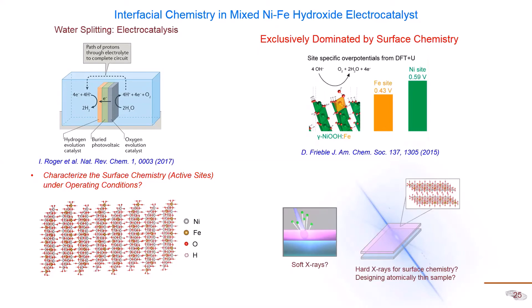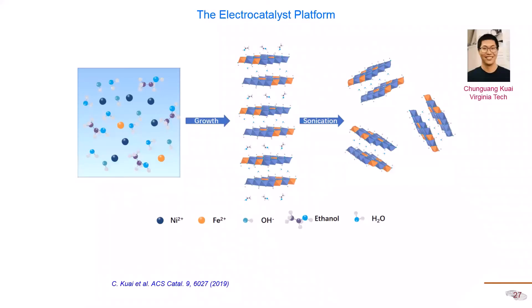Chunguang Kuai performed better visualization through wavelet transform analysis of the EXAFS to differentiate iron-iron versus iron-nickel neighboring. Upon charging to 1.6 V, the iron-nickel coordination (neighboring) disappears. Upon recovery, it shows up again. These are snapshots of experimental evidence showing reversible segregation and incorporation of iron into the lattice. We then designed a protocol leveraging this reversibility — periodically applying a short two-minute reduction step at 1.33 V during operation to incorporate iron back and revivify the electrocatalyst, successfully sustaining cycle life.